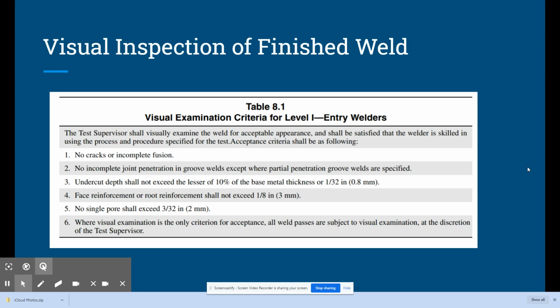Face reinforcement or root reinforcement shall not exceed 1/8. Well, again, this is a backing strip weld, so we can't measure root reinforcement like we can on an open root weld. But face reinforcement, this is probably one of the harder things that students have a hard time passing, not getting that bead too tall off the base metal. We'll talk more about that in the inspection videos.